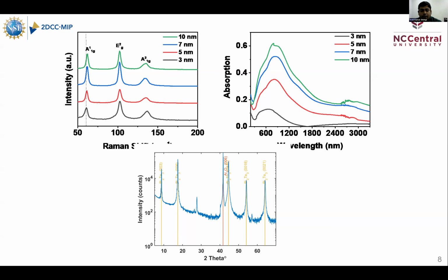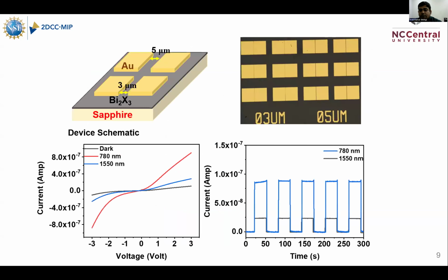This kind of trend I want to realize in terms of devices. So for this, we prepared devices with different channel lengths: 3 micrometer, 5 micrometer, 7 and 10 micrometer. I characterized the 5 nanometer thick bismuth selenide sample with 5 micron channel length using 780 nanometer and 1550 nanometer LED light, and we've seen good photo detection data.